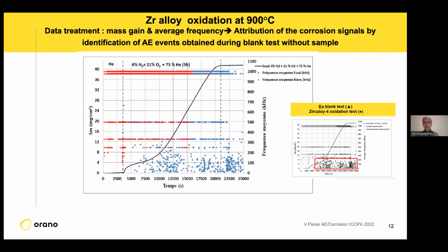So we have done the treatment under air at high temperature on the zirconium alloy, and then we have recorded the mass gain, but also the acoustic emission events coming from the sample. Before that, we made some blank tests, because that is very important in acoustic emission studies: we have to distinguish the noise due to the heating of the furnace and people coming into the room near the experiment from the events only coming from the corrosion.